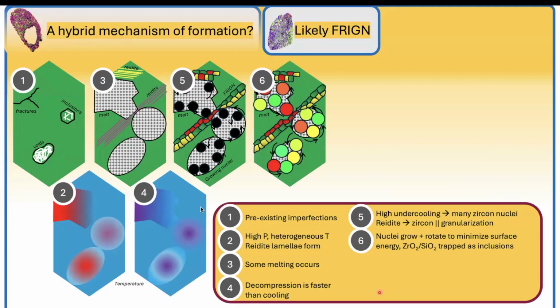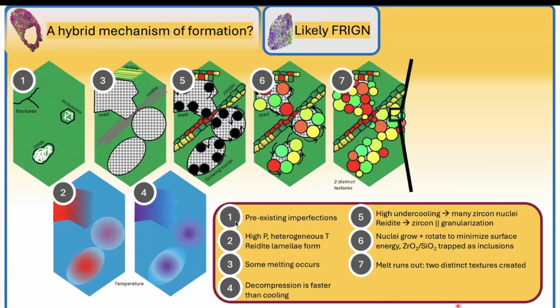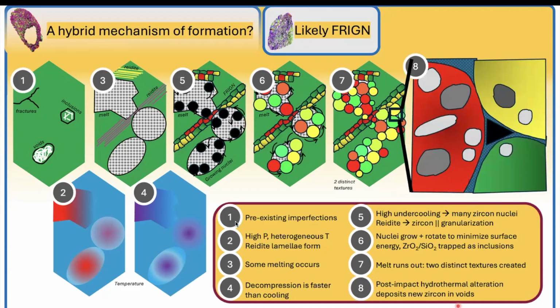The difference here is that I'm saying that these nuclei kind of remain closer to the edges. So they take a crystallographic blueprint from that back transformed Reidite, from the Reidite that's still there, and from zircon that's still there. As they're growing, this is a melt or a partial melt, so they trap inclusions of zirconia and silica. Eventually, the melt runs out. You get two distinct textures in the same grain, and you get this kind of structure.